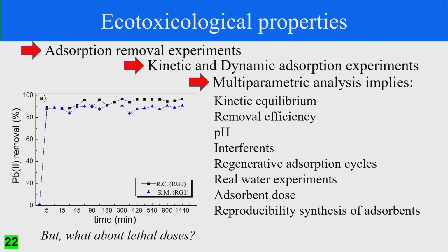When we perform adsorption removal experiments, kinetic and dynamic adsorption protocols must be performed. It implies that we have to do a multiparametric analysis, including kinetic equilibrium, removal efficiency, pH, interference, regenerative adsorption cycles, real-world experiments, and to analyze the adsorbent dose and reproducibility of the synthesis of the adsorbents. This is really important. But what about the lethal doses? We don't know.